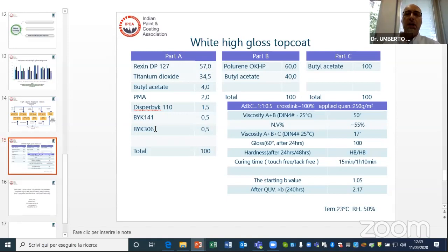Again, I can show you a formulation based for a white gloss coat. In this case, we have a pigmented system. The formulation is based on Rexin DP127, and the isocyanate this time is Polurene OKHP that allows us a better resistance to light. We can see we have a good level of solids. We can reach a gloss of 100. We have a good level of superficial hardness, and we have a curing time that is very good for a glossy system.